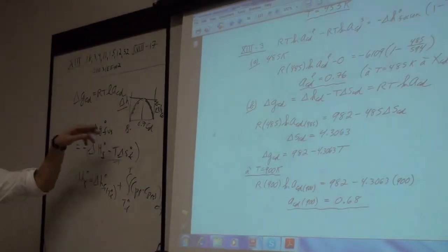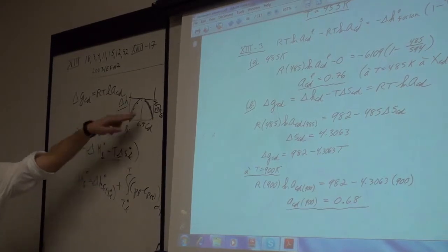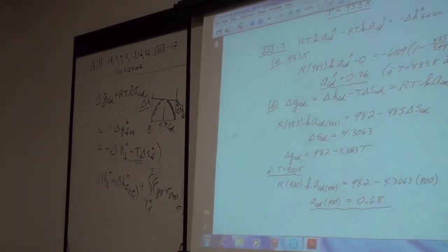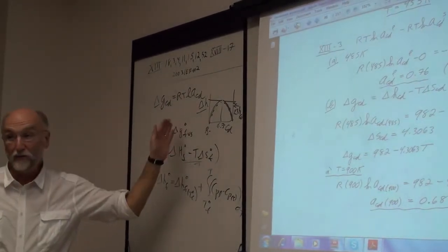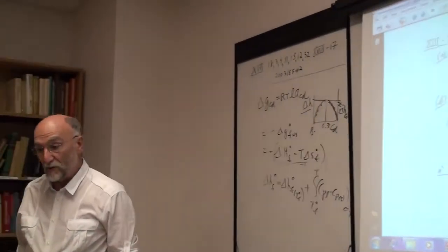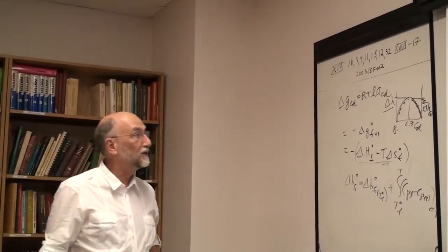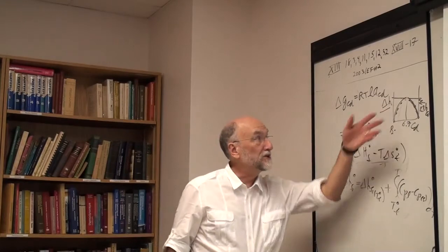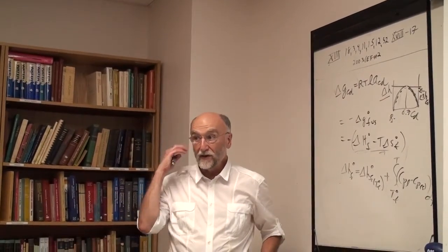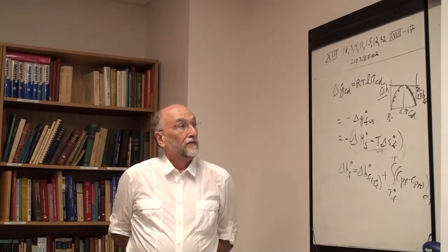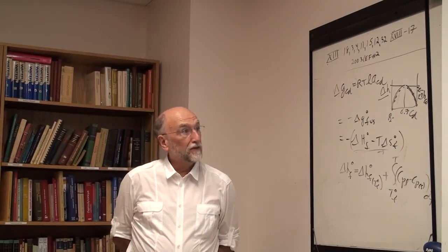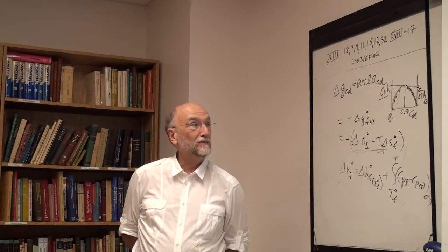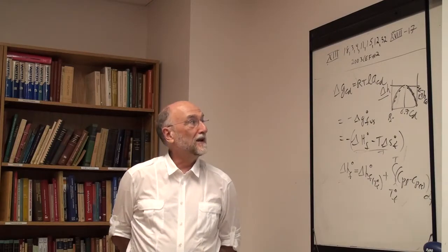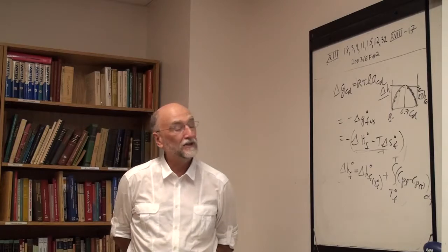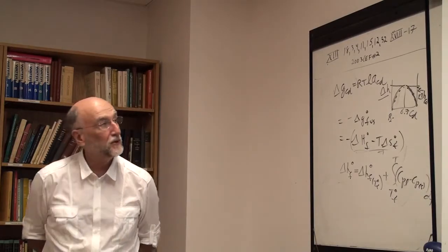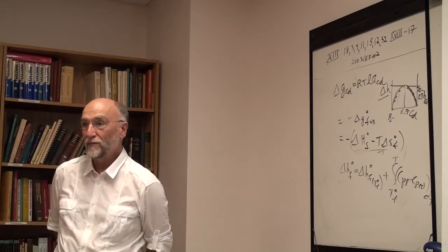Okay, otherwise, this would only be the partial heat of mixing. The heat of mixing and the partial heat of mixing also are not independent of temperature. They depend upon delta Cp of mixing. But in most of these high temperature things, as long as we're dealing with a reasonably small temperature range, it's a reasonable assumption to assume that the heat of mixing is independent of temperature, although this is an assumption that is probably made too often. Sometimes we make that assumption and it really isn't justified. On the other hand, delta Cp of mixing is rarely a very large value, so it's a halfway decent assumption.